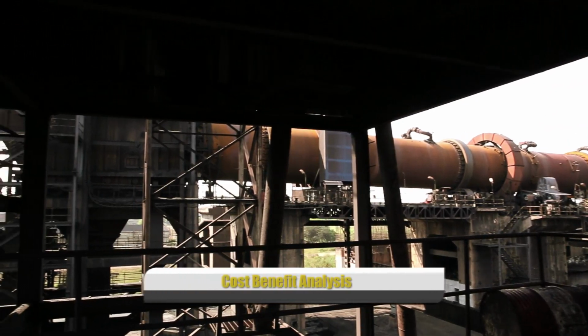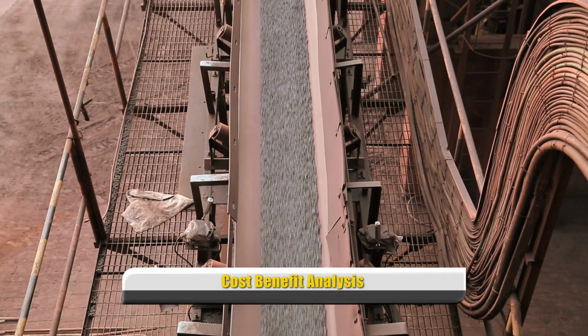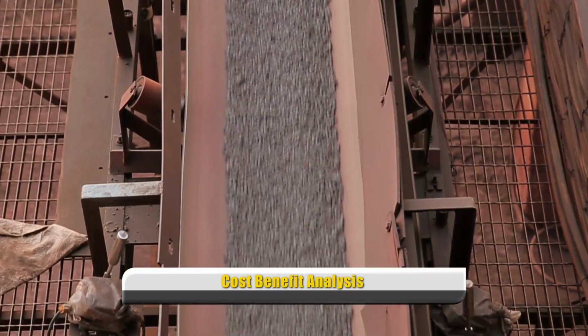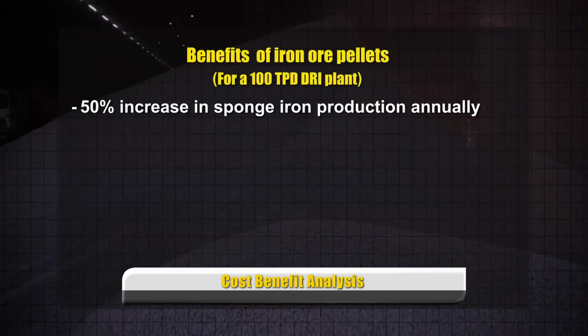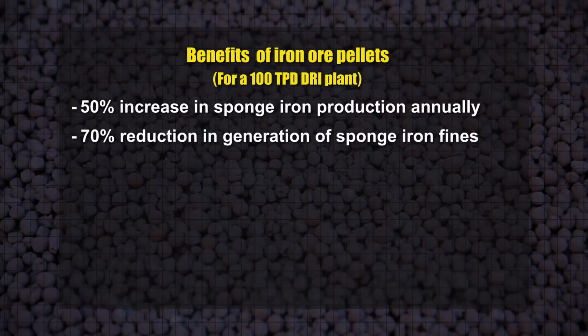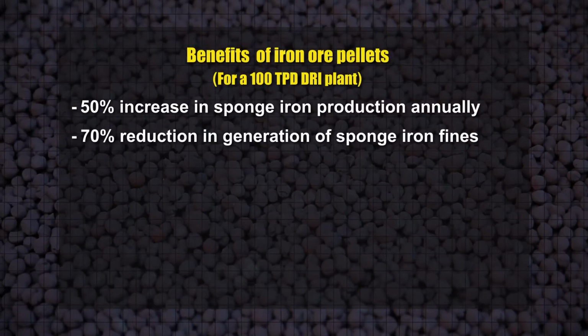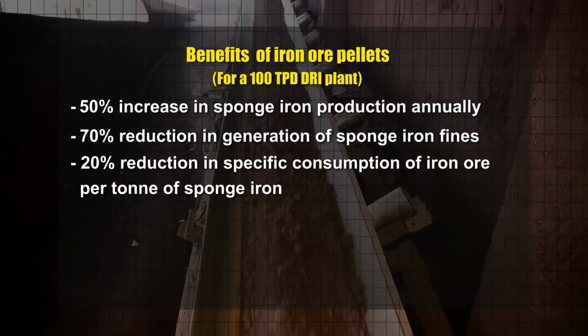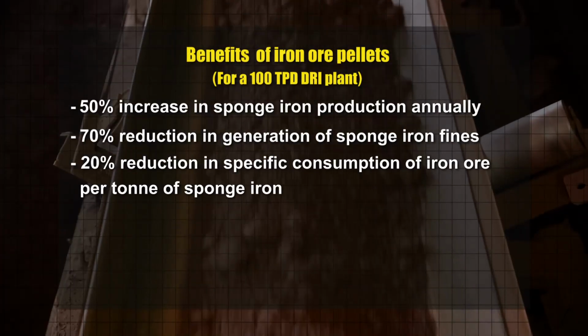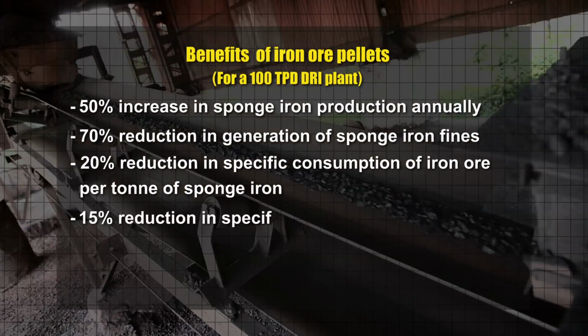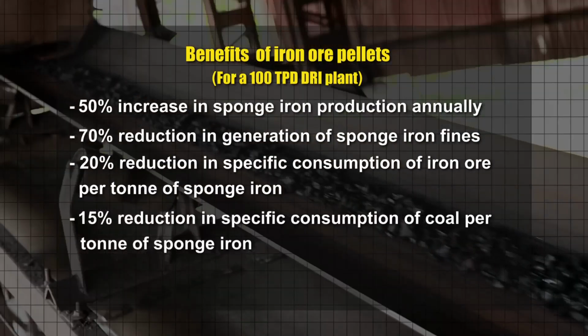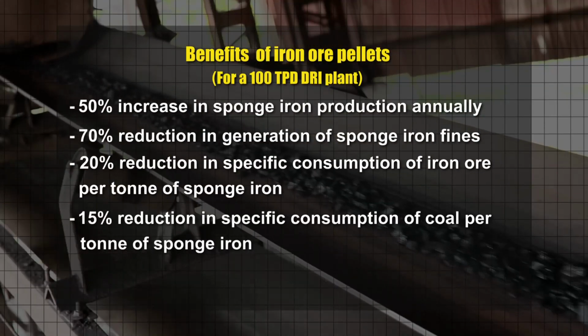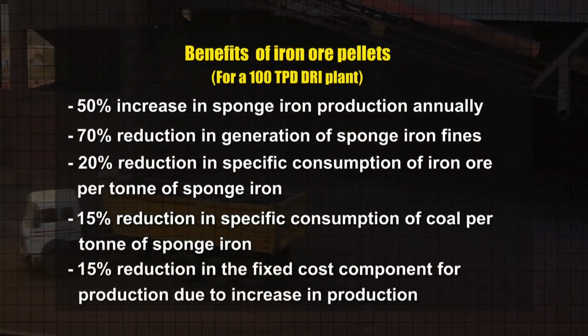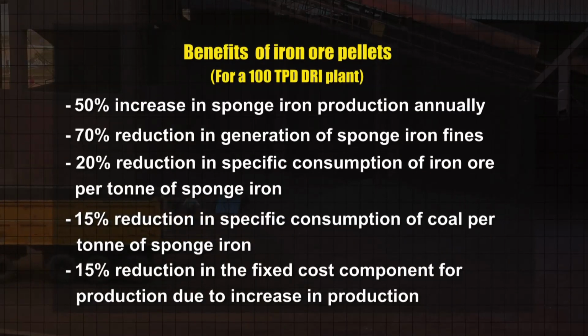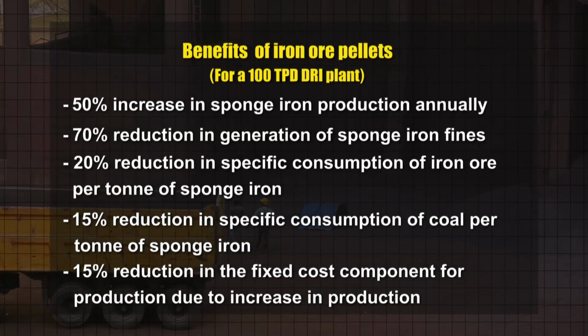For a 100 TPD DRI plant, use of iron ore pellets vis-a-vis lumps leads to the following benefits: 50% increase in sponge iron production annually, 70% reduction in generation of sponge iron fines, 20% reduction in specific consumption of iron ore per ton of sponge iron, 15% reduction in specific consumption of coal per ton of sponge iron, and 15% reduction in the fixed cost component for production due to increase in production.